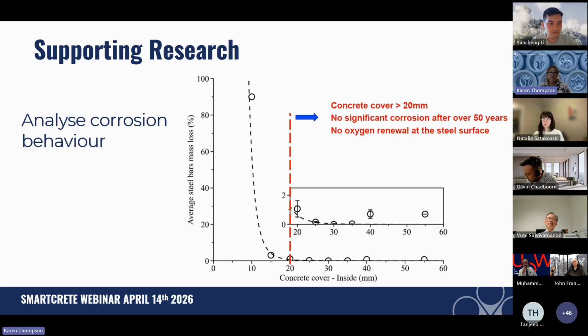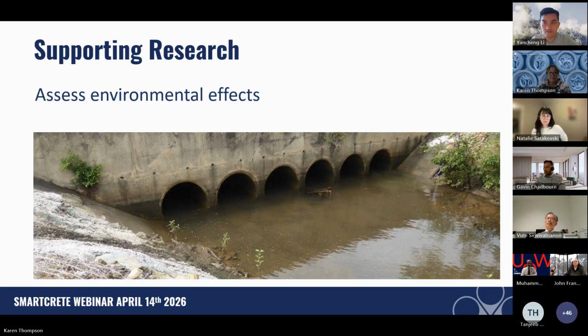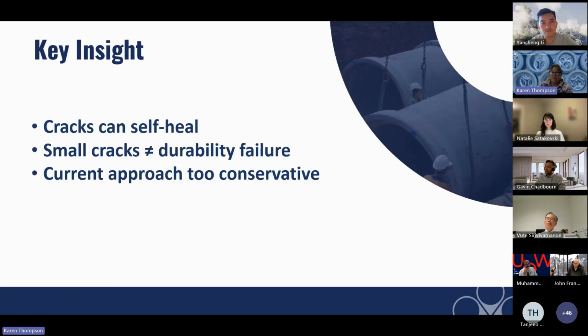Research on exhumed concrete pipes in the past has showed that there was no significant corrosion after 50 years in service. This project seeks to further consolidate on the past research by investigating the corrosion of reinforcement in concrete pipes in aggressive environments that stormwater pipes may be subject to. And assessing the environment, like where the pipe is. Pipes are buried structures, and so it's in a completely different environment underground to most concrete structures. And so the environment that the pipes are in is important.